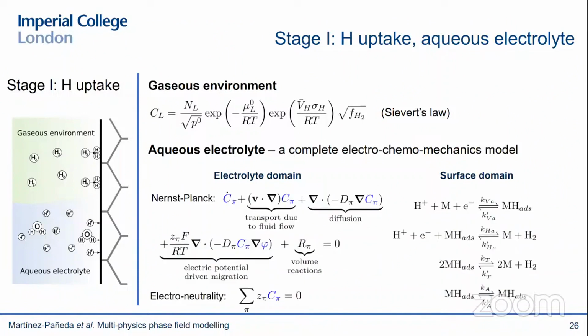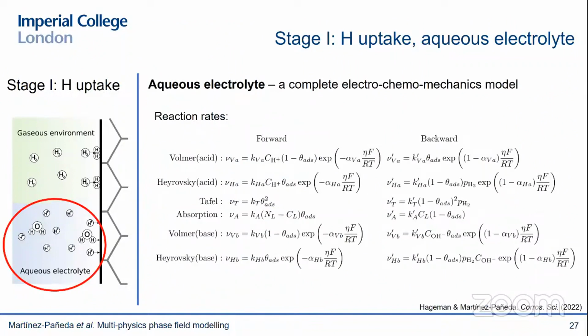This means that the kind of theory that we can come up with means that we're solving the Nernst-Planck equations for as many ionic species as needed in the electrolyte domain, and then you're solving the Volmer-Heyrovsky-Tafel and absorption reactions in the surface of the metal. And this is in addition to the other, well, these are the surface reactions, by the way. I'm not going to get into details, but the key point is that the model is physically based in that it doesn't require any prior assumptions.